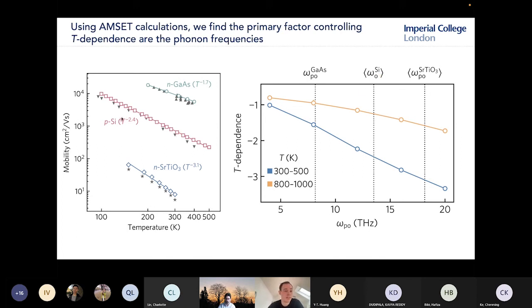Silicon, p-type silicon, has a very different scattering physics. It's not polar at all. And actually, in the p-type case, you're really dominated by optical phonon scattering. So if we take the average optical phonon frequency in silicon and read off from this plot, which is again determined just using polar optical phonon scattering, but we'll misuse it for now, the expected temperature dependence is about -2.5 or -2.4, which is again very similar to what we see in experiment.